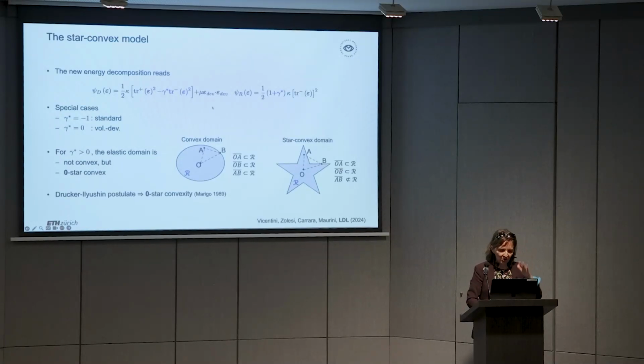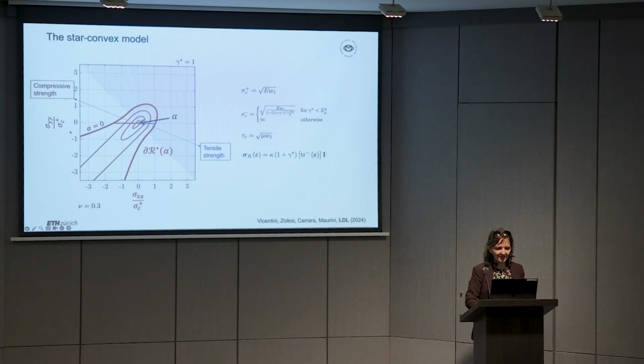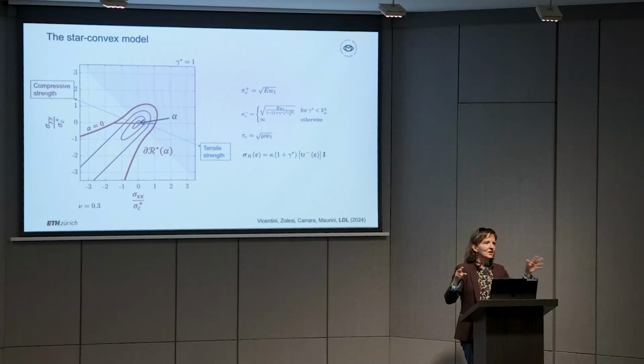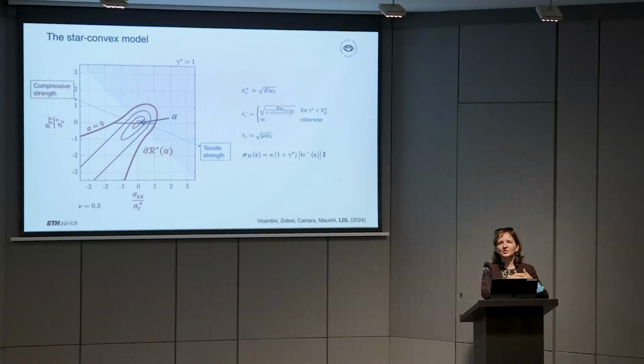This model ticks all the boxes, but the drawback is that this model gives us a non-convex strength surface, which however is star convex. So this can be shown that there are no issues with thermodynamics, because, if you're familiar with plasticity, you know that you want the strength surface, the yield surface in plasticity, to be convex, because this will automatically guarantee for you thermodynamic consistency. In this case, in damage, a star convex surface already gives you thermodynamic consistency. So that was not the issue. The issue is rather that a star-shaped, star-convex surface is not very realistic.